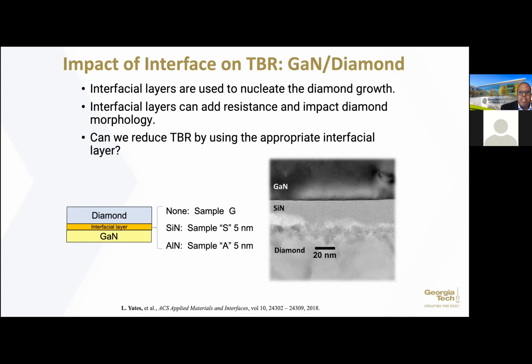So what we've done here is looked at the impact of some of these interfaces on the thermal transport behavior. And so I have GaN, I have diamond, I have the silicon nitride, which is commonly used. So we said, what if we take the silicon nitride and just thin it down to 5 nanometers? What if we replace the silicon nitride with aluminum nitride, 5 nanometers? And then what if we take this sample and we don't have an interlayer material and we grow the diamond directly on the gallium nitride? What happens?